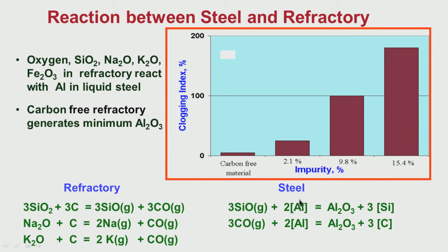This SiO will now react with aluminium in liquid steel. I have mentioned many times that we deoxidize the steel. A good amount of deoxidation is possible only when we do deoxidation or killing with aluminium. So, some amount of aluminium will also be there as elemental aluminium in liquid steel. This elemental aluminium will react with the SiO forming in the refractory from the reaction of SiO2 and carbon, and this will generate alumina and silicon